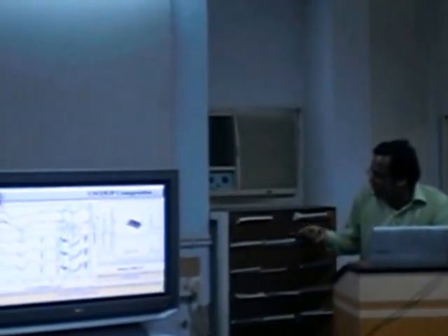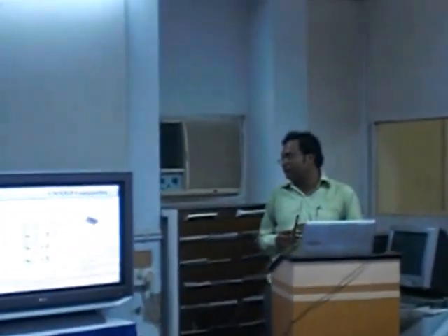And we have done the FTIR spectroscopy. This one is the pristine carbon nanotube. This one is the functionalized carbon nanotube. And we have done the unsaturated polymer matrix, and we have found there might be a possible interaction of the functionalized carbon nanotubes' carboxyl and hydroxyl groups with the free radicals in the unsaturated polyester matrix.